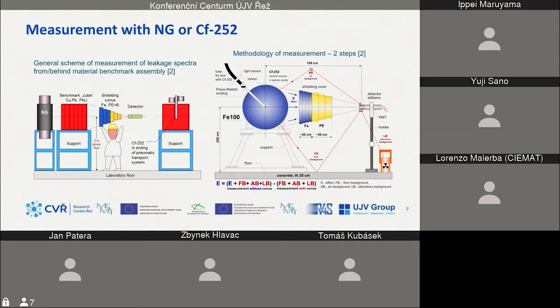The basic principle of the measurement performed in our laboratories is described in the second picture on the right side. This is the case of a sphere of pure iron with a diameter of 100 centimeters. Inside there is the isotopic neutron source, and you see something like cones here. Why do we do it this way? Because each measurement has to be performed in 2 steps. One is a measurement without this shielding cone. So we measure everything: all the signal, the useful signal from the assembly, scattering from the air, floor, other sources placed in the laboratory, and the walls.